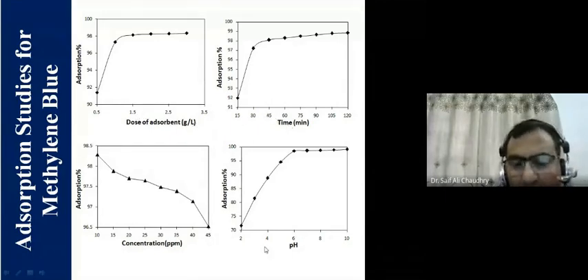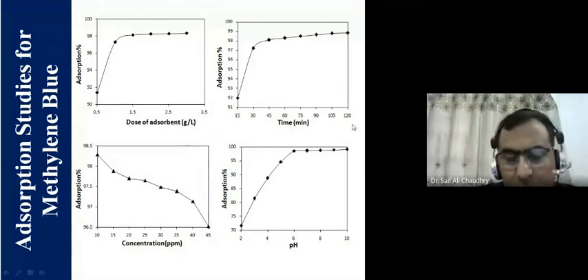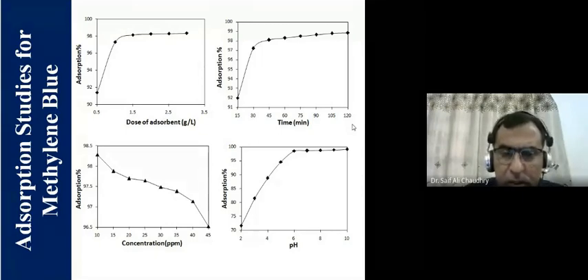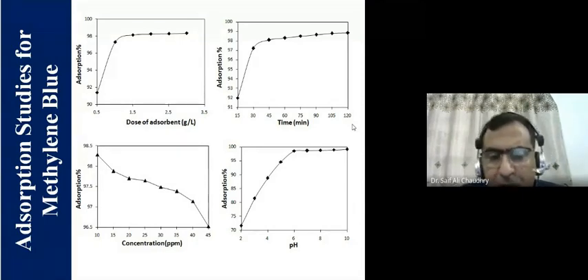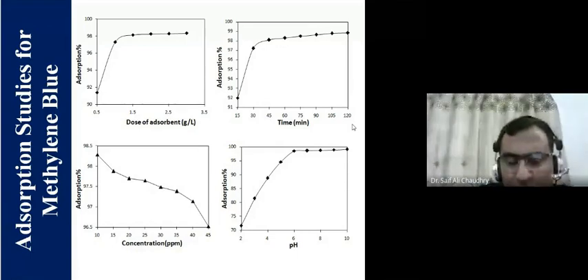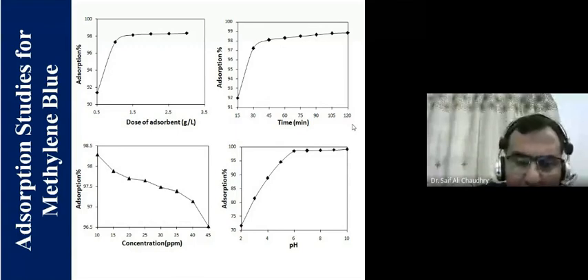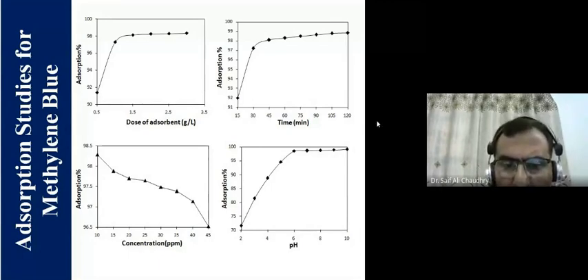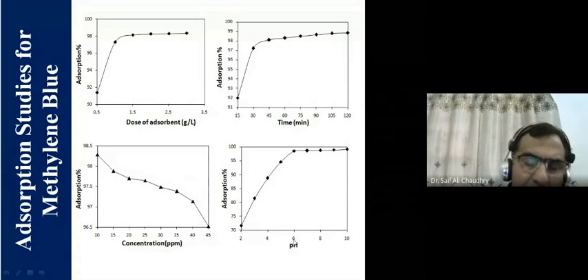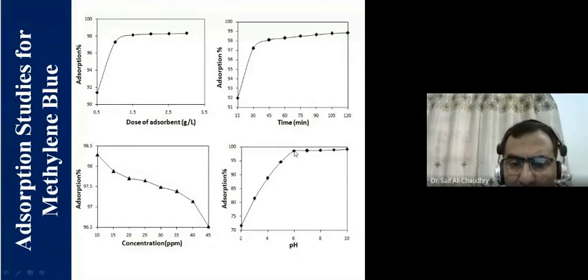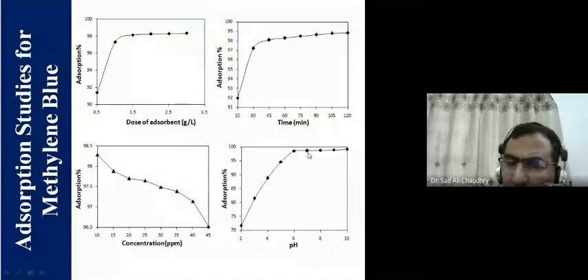Now the effect of pH is important when you have to apply the technology on real situations, and water or the wastewater coming from an industry. The industry uses a lot of acids and bases, and ultimately the pH of the water is altered, and we must know how effective the change of pH is on your system adsorption. Now this was a ZPC, zero point charge, around 6.6 and 7. Therefore after 6 or 7, or nearby 6 to 7 or other neutral condition, the material was very good, or it was effective.